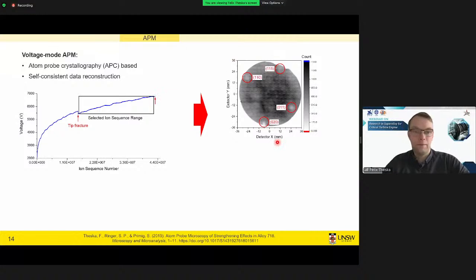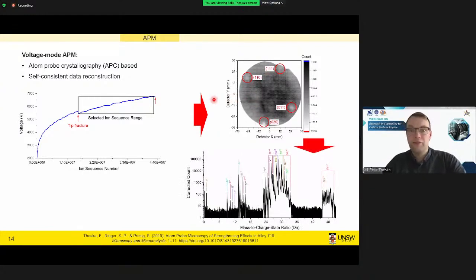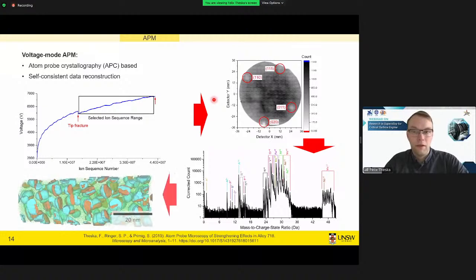Remember, that's this two-dimensional detector, and we see there are some regions that give us less signal. And sometimes that can be crystallographic regions, like in this case. We then have a look at the mass spectrum and can assign each peak an element. And once we have calibrated these reconstructions, we get these very nice 3D element maps.